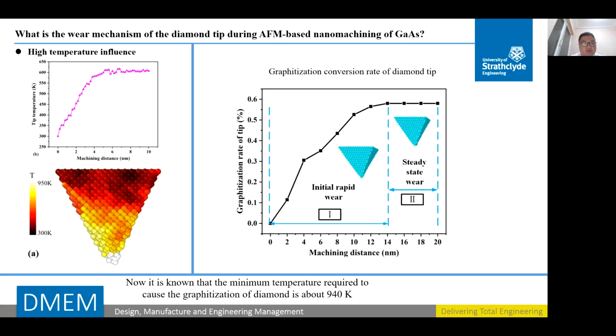It's known that the minimum temperature required to cause graphitization of diamond is around 940 Kelvin, which is basically the same as the high temperature of my simulation result. Therefore, it implies high temperature at the apex of the diamond tip might cause graphitization. From this figure, we can see it includes two stages. The first one is growing graphitization, which implies initial rapid wear before 14 nanometers. Later stages of wear were somewhat steady. Therefore, this curve suggests that continuous graphitization of the diamond tip might result in tool failure during nanometric cutting of gallium arsenide.